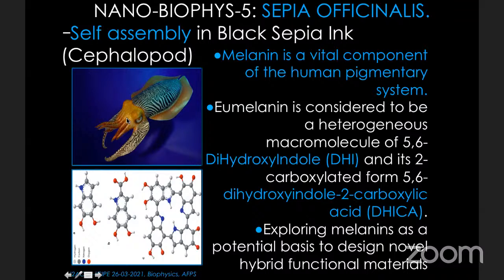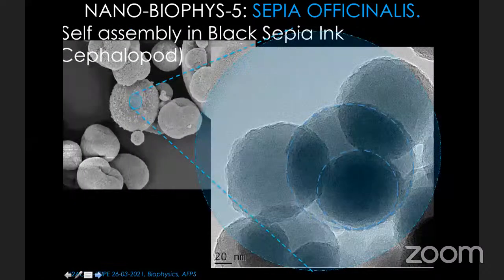So we investigated their properties. And we found out that if you get the powder of this black ink, in effect, they are a form of toroidal, large toroidal particles. And if you zoom and you go to single out some particles, you will find out that you have spherical nanoplatelets, truly spherical nanoplatelets.